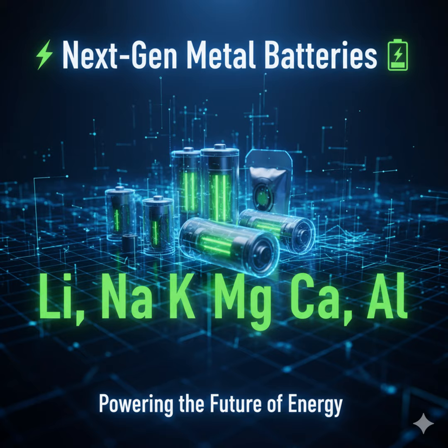You use electrolyte solvents that are really good at grabbing onto the metal ions, strongly solvating solvents, things like DMAC are mentioned. These aggressive solvent molecules essentially muscle their way in, surrounding the Mg2+ or Al3+ ion and pushing the anions further away. So you're using strong solvents to pry the cation and anions apart. Exactly. This encourages the formation of an SEI that's derived more from the solvent, making it more organic-rich, rather than from the anions. The goal is to create an SEI that's still protective, but allows those Mg2+ or Al3+ ions to actually pass through, enabling the battery to work.